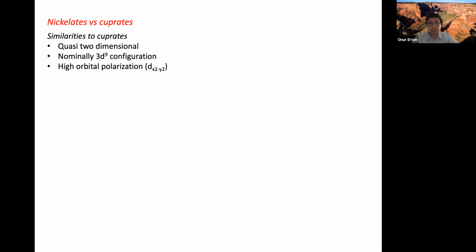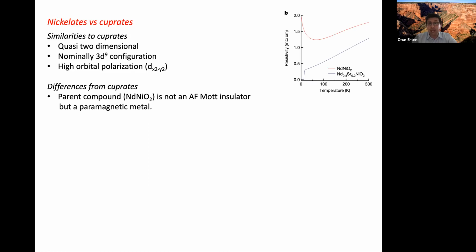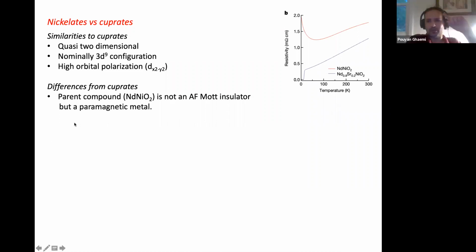It's similar to cuprates. But what are the differences? As Pouyan pointed out, the parent compound is not an antiferromagnetic Mott insulator, but a paramagnetic metal. I call this a metal, but the resistivity increase is not even twofold. It's just disorder, in my opinion. Or you can call it a bad metal if you want. So this is a big problem, because I've been telling you that unconventional superconductors arise near a magnetic phase when you suppress magnetism.